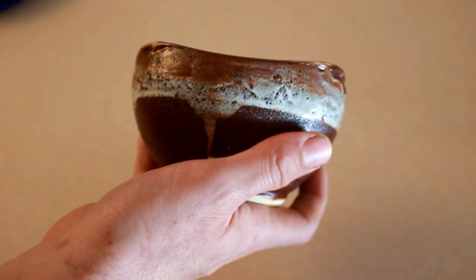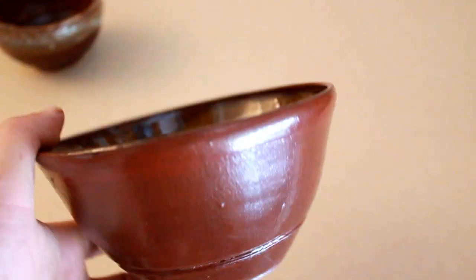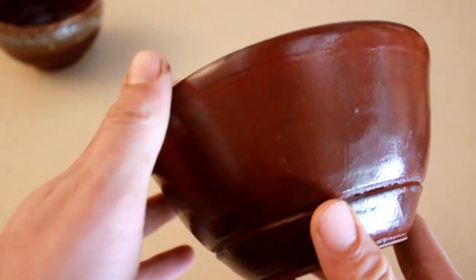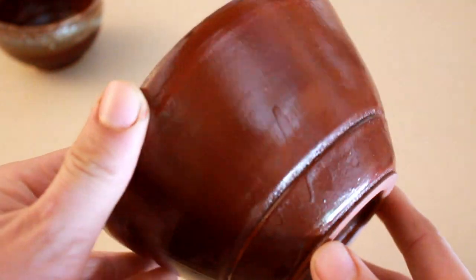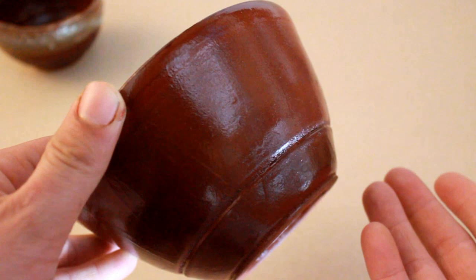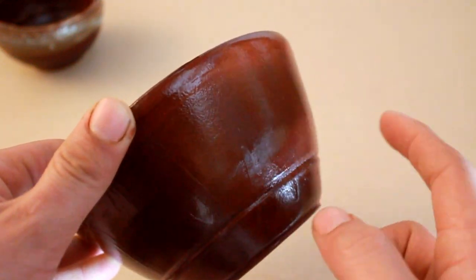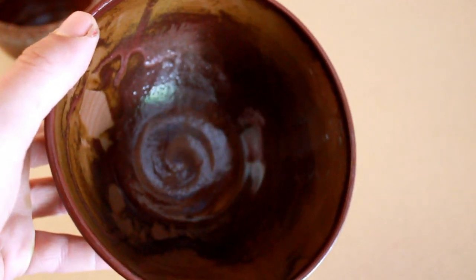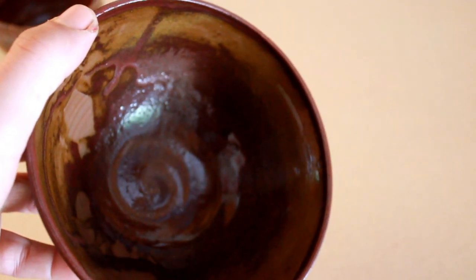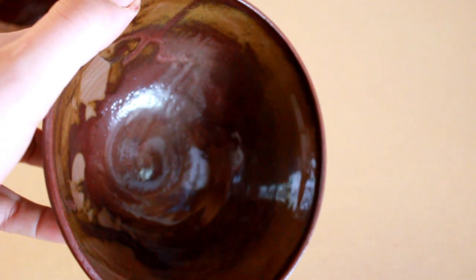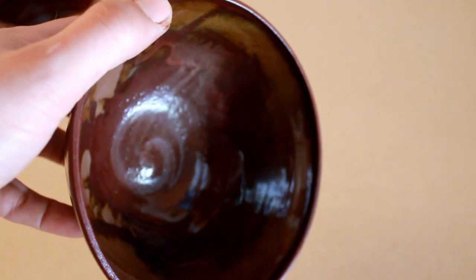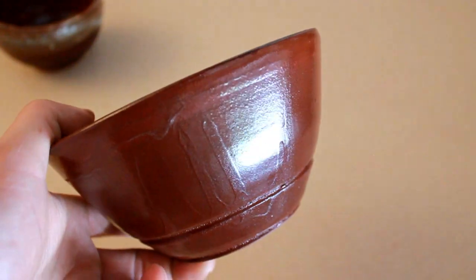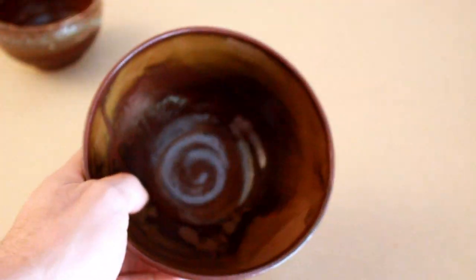This, we're gonna call this one a failure right here. This right here is pretty much the same exact thing, except for you can really see the entirety of the glaze I was experimenting with on the outside. And of course, because it's an iron glaze and I didn't put a hold on it, it turned brown like doo-doo. But the major reason this is on the bottom slot is because you look inside, and there's some really good colors, but there's also a lot of crawling. So I'm gonna call this glaze a loss. I'm gonna put it in my notebook as a glaze that I'm not gonna use in the future, unless I can get a kiln that can put a hold, because it's really difficult to do a hold in a manual kiln. Get out of here, we don't love you.